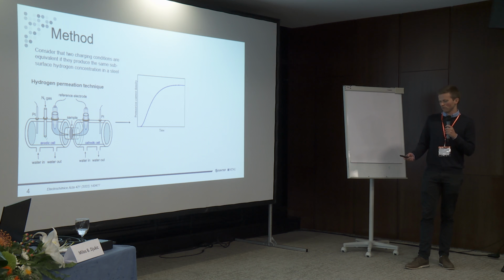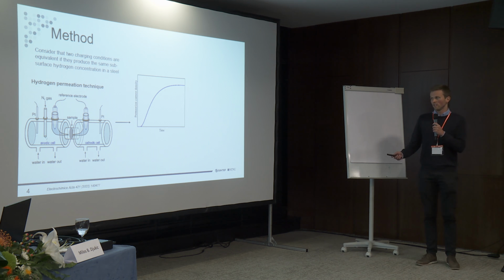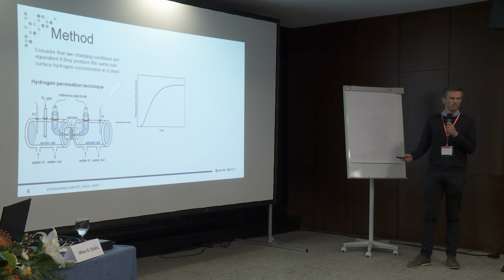So the result will look something like this. You have this S-shaped curve, and on the y-axis you have the permeation current density or hydrogen flux, and you have the time on the x-axis. And from this curve you can determine the diffusion coefficient and subsurface hydrogen concentration.